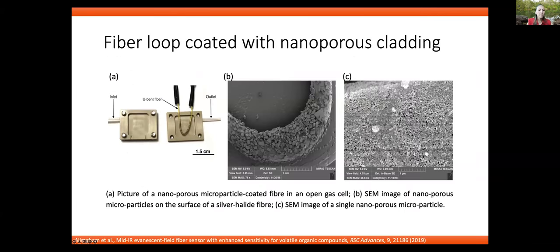So what we did here, we took our fiber and then we took the membranes and we put them in a sonicator, which effectively destroyed the membrane completely. And it created microparticles that have nanopores. So in a microscale here, we can see those relatively large particles coated on top of a fiber. And if you zoom in on one particle, you can see it has the nanoporous structure. And those nanopores will absorb the VOCs from the environment.